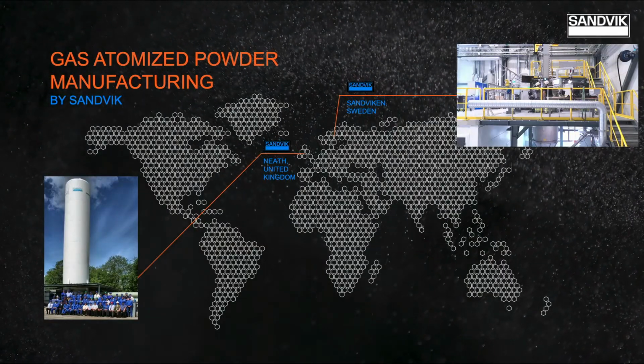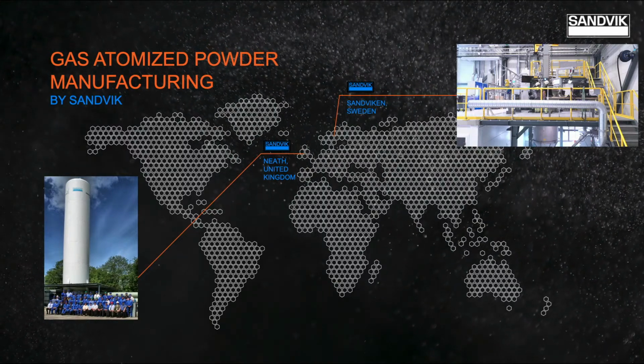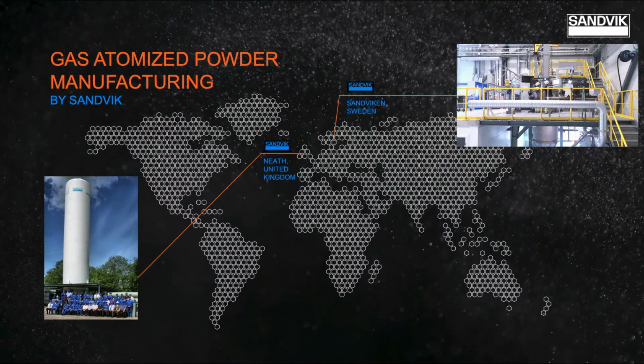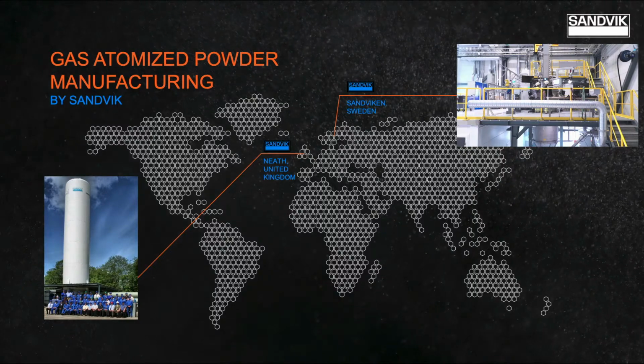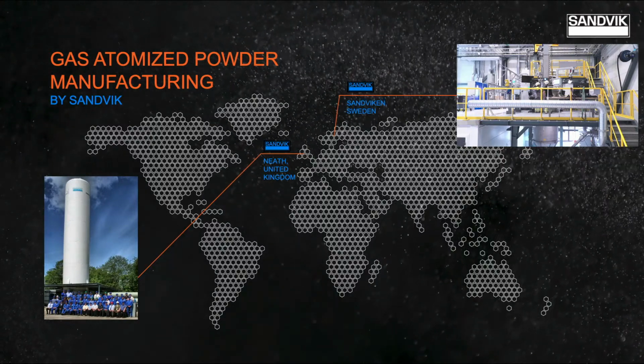Certainly, Peter. Thank you. Well, the key parameters for metal powders include, of course, the chemical composition, the powder size distribution, and the shape or the morphology of the powder, which all combine to influence the flow characteristics of the powder, which are very important for additive manufacturing processes. We actually manufacture powders in the UK, based at Sandvik Osprey, which is in a small town called Neath in South Wales, where we have 8 inert gas atomizing towers, operating both argon and nitrogen gas, with a unique set of powder sizing capabilities from large industrial sieves to air classification units, producing powders with an average size between 80 and 5 microns. And one of the atomizing towers is dedicated to aluminium powders, and the entire facility is certified to AS9100D aerospace certification.